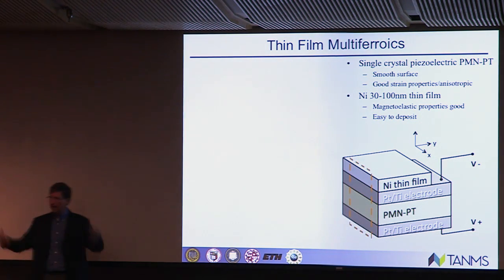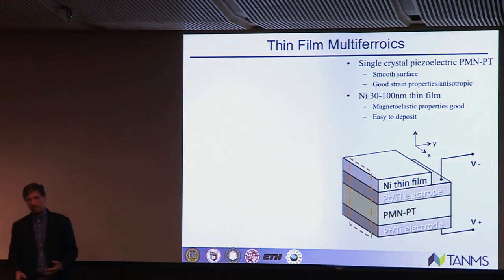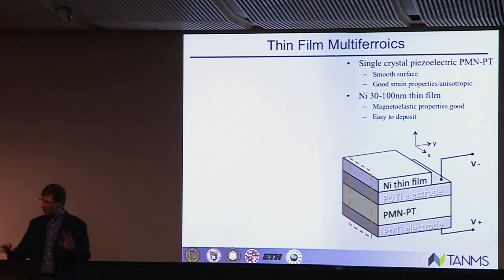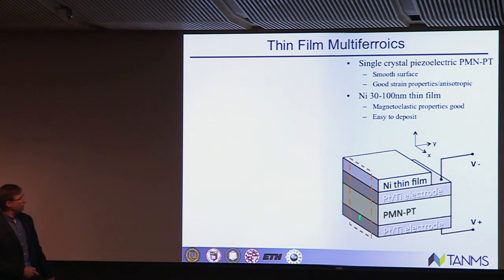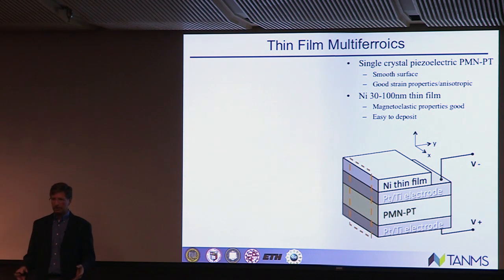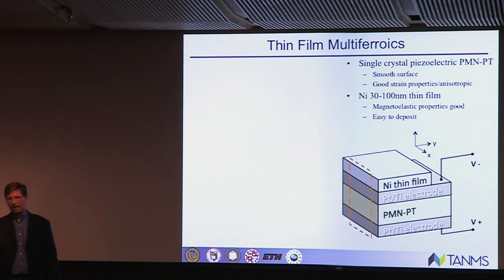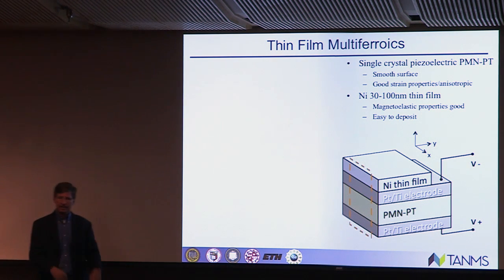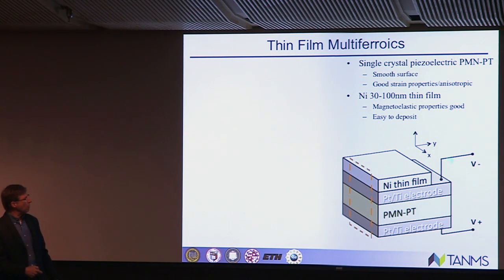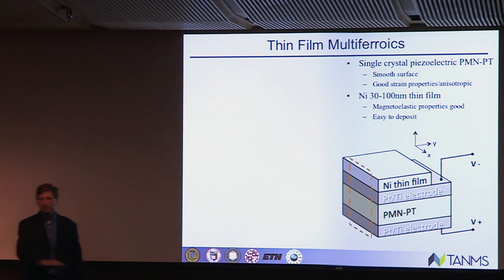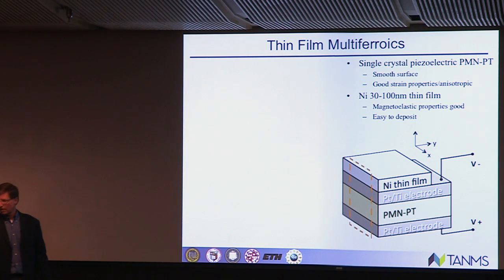So enough motivation. Now let's talk a little bit about research. So what you're going to see first, let's talk about the structures. The first thing is we're going to focus on a PMN-PT as our ferroelectric phase. It's single crystal. And you should be asking, well, why do you want PMN-PT single crystal? Comment number one is all the structures we're talking about are nanoscale, so we need an extremely smooth surface. So I can get this with actually 1 nanometer roughness.